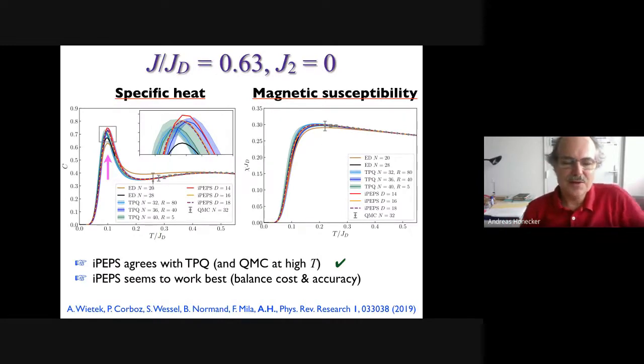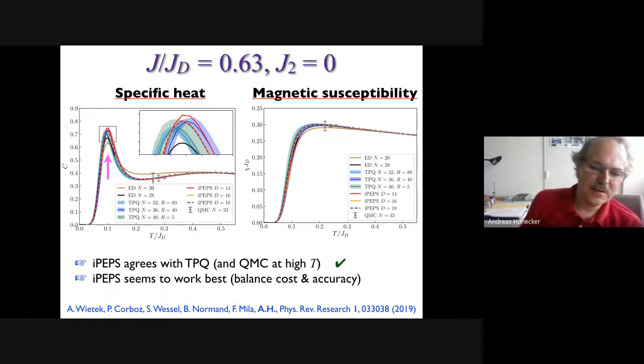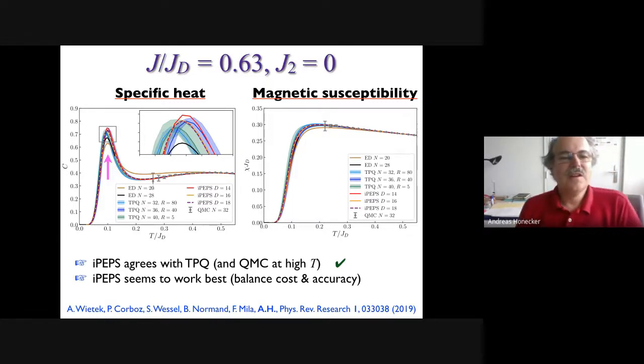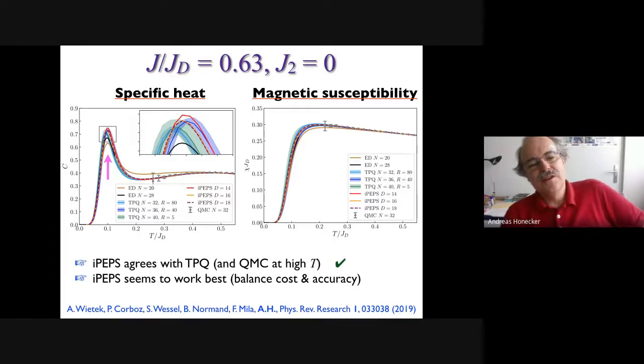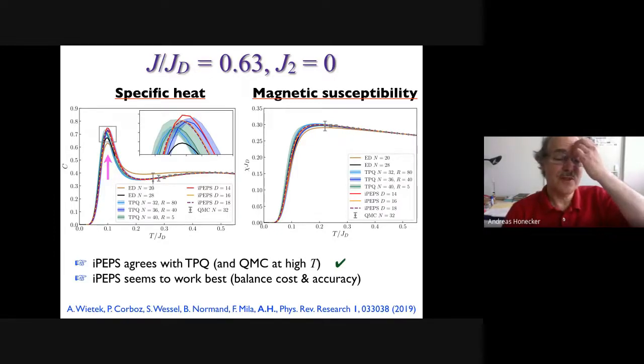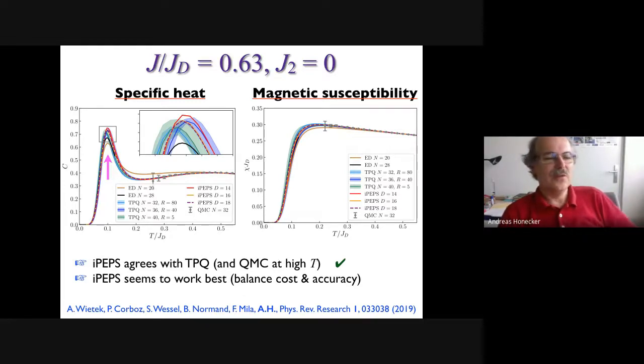And here I'm showing you again the ratio relevant to strontium copper borate. And now I'm comparing here, in red, well, maybe you should take the magenta dashed line, that is iPEPS for the lowest degree of approximation, so with the lowest bond dimension. There's this internal bond dimension parameter that you need to crank up to make it more accurate. And then if you compare this with thermal pure quantum states, you see that basically the iPEPS and the thermal pure quantum states are indistinguishable.